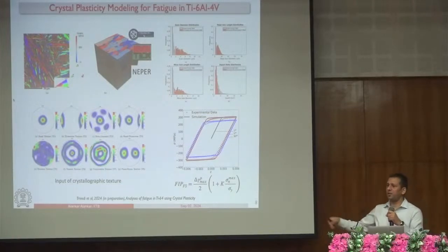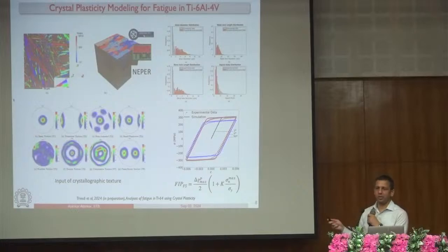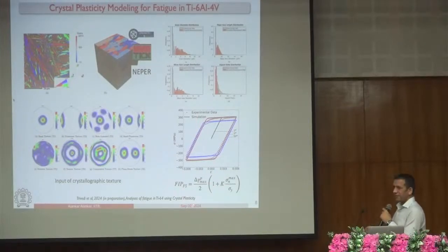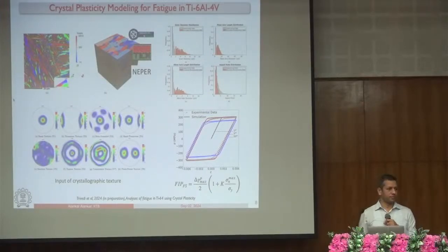So that has already reduced the amount of effort that I could have put, right? On top of it, we are calculating these fatigue indicator parameters, which are functions of how much plasticity has happened in the material, which is given by this delta gamma. It is also capturing on what plane the shear is happening, on what plane the crack will initiate. That is also being captured in this FIP, right? And still the simulations are expensive.